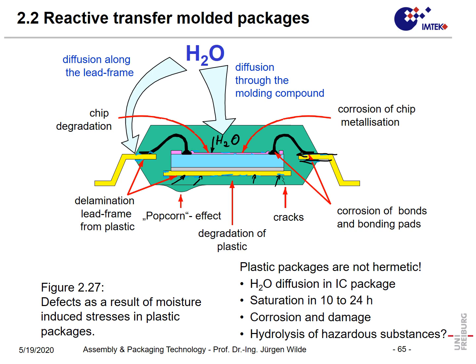So what's the effect of the water? The effect can be on the chip surface, for instance, a corrosion of the chip, especially of the metallization. We can have a degradation of the chip by moisture that penetrates in. Also, electrical properties could be changed just because water is conductive. Then there can be delamination of lead frame from plastic. We can have delamination of silicon from molding compound. And all of these phenomena are not desired. And we must keep in mind that the main barrier against water is this passivation, which is on the active area of the chip.